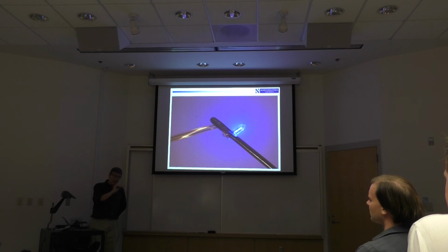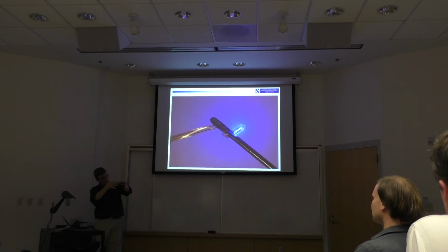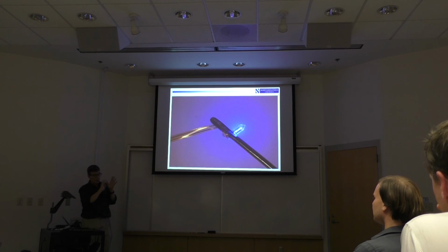And every material that we've ever looked at that you deposit into films of that thickness inevitably has some pinhole defects, just structural imperfections, or you're depositing this material on a heterogeneous substrate that has topography associated with the devices and it doesn't completely cover the edge or whatever, all kinds of different things. Because one failure across a several centimeter square area of electronics and you're done. I mean, it just takes one pinhole and it's over.